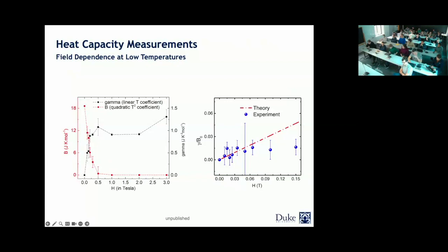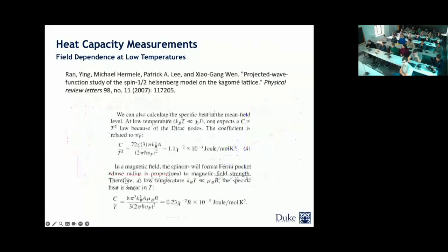If I go back to your formula and your basic data, it seems to me that if the main content of this formula is that if I believe in the slope at zero field, that is equation 4, and I know what the Bohr magneton is, then I just know quantitatively what the zero temperature intercept of C over T is as a function of B. So why isn't there just a plot of intercept versus B, the C over T intercept versus B, just using real numbers, using the A and A over VF squared and so on, obtained from equation 4?